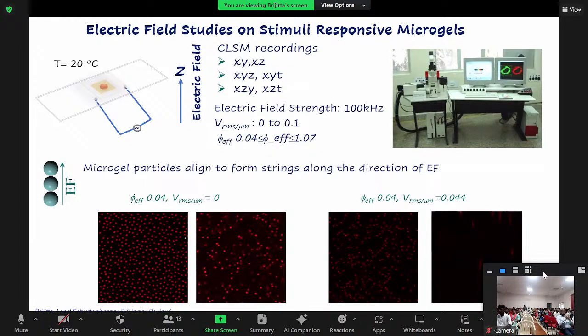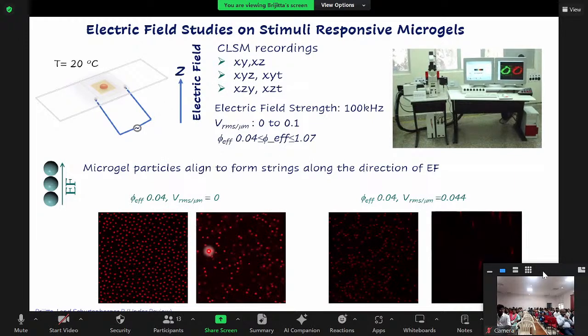So in a dilute sample, which is shown here, you can see that the particles are in a random motion, and when you apply field, you don't see much change here. It's almost the same, but only the number density has changed. But here in the case of the next sample, this is the same, there is no electric field. Here the electric field is about 0.044.